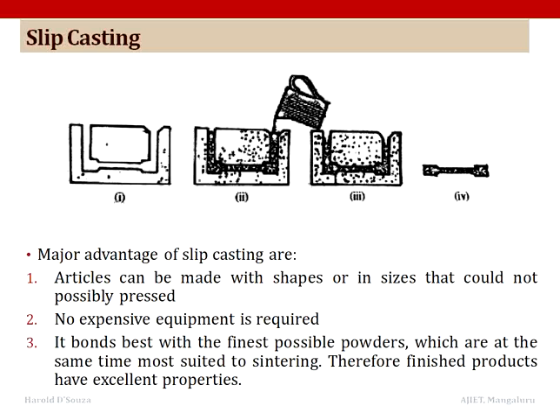These ingredients interact, especially in their competition for binding sites on the powder surface. For this reason, the order of addition of components and their mixing time are also important variables in making the slip. The formation of an appropriate and a consistent slip is important for a successful slip casting. This is usually achieved by maintaining a proper control of particle size and size distribution. The addition of proper deflocculants which prevent the settling and aggregation of the powder particles maintains the desirable viscosity of the slip.